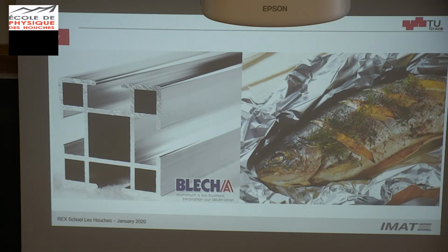Not the fish, but the aluminium foil, because it requires a lot of rolling steps. So warm rolling, hot rolling, warm rolling. And then at the end, you cannot heat up again, take it from the furnace and roll again, because the heat transfer is very fast. Then you end up with cold rolling, and in between a lot of steps for recrystallization and also for precipitation. So it has a lot of complexities.